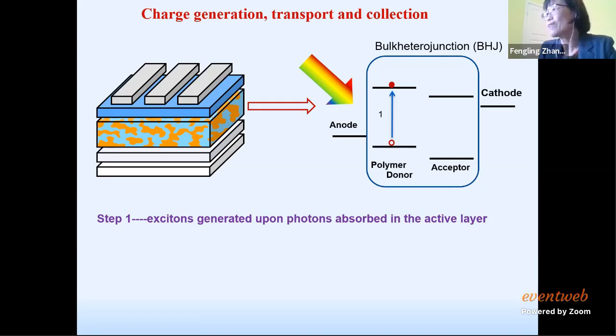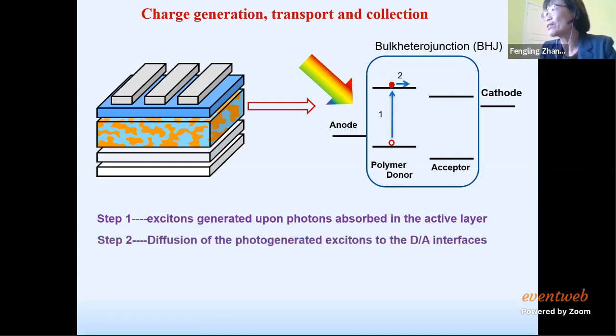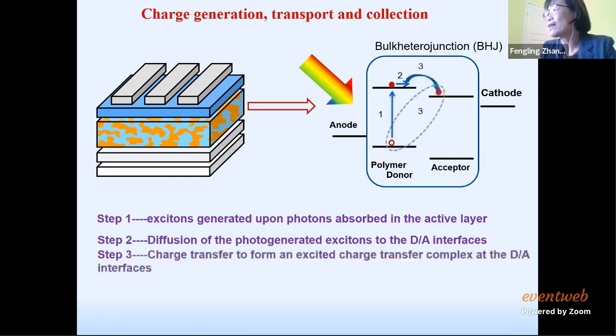Then they form the, actually not free like in silicon where they become free charge, but here it's still bonding, but loosely bonding, from the exciton. So exciton will diffuse in the bulk heterojunction. If they reach the interface between donor and acceptor, then there is possibility for the electron transfer from donor to acceptor. Then they are still bonding, but even weaker bonding, with larger distance between them. Therefore, this bonding will easily dissociate into free charge carriers.